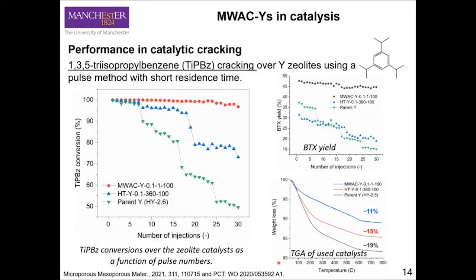And then we tried catalytic cracking, and we used 1,3,5-triisopropylbenzene, which is quite a bulky molecule, as the model compound to probe the effectiveness of the mesopores generated by this new method. So we have the parent over here. You can see the deactivation is very fast because this molecule has a kinetic diameter much larger than the intrinsic pore size of the parent zeolite Y, which is 0.74 nanometer. Therefore, the large molecule can potentially coke outside of the crystal and deactivate it.